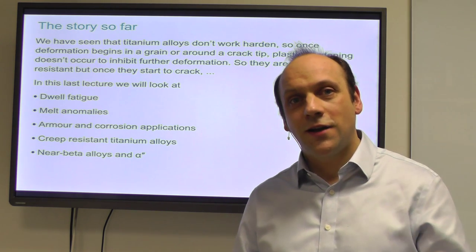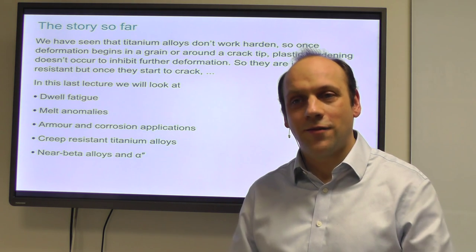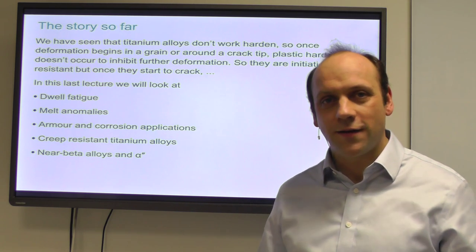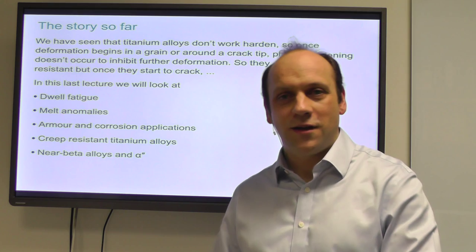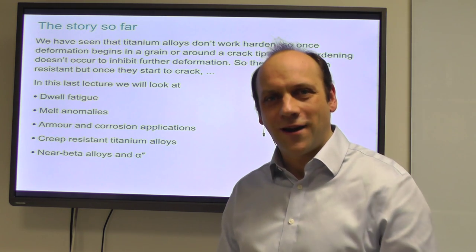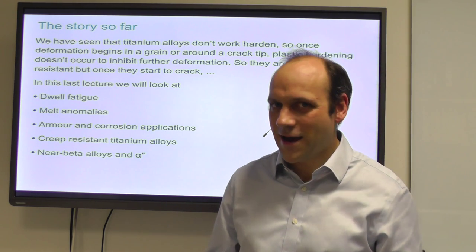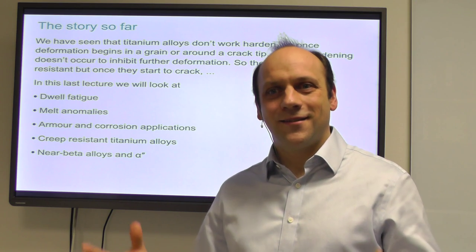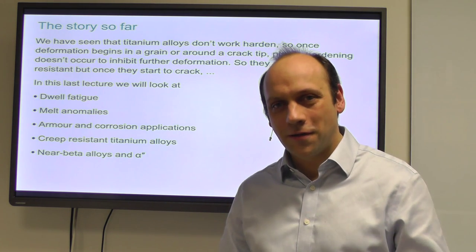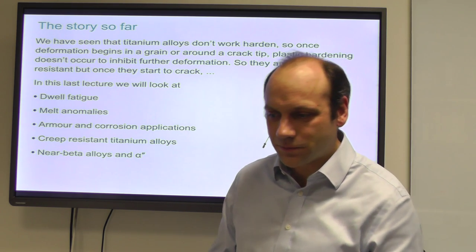So they're initiation resistant for fatigue, but once they start to crack, then the fatigue crack growth rates can be quite quick. So most of their lives are spent in the initiation step. Fatigue crack growth step is relatively fast. In part, that's because we're using them at such a high stress, right? If we use them at a lower stress and lifelong fatigue crack growth, we'd be okay. But the attraction is that they're fatigue resistant, we can use them at high stresses. So then they spend most of their lives initiating the crack, and once it starts to go, it goes.